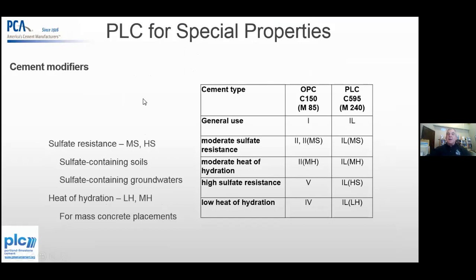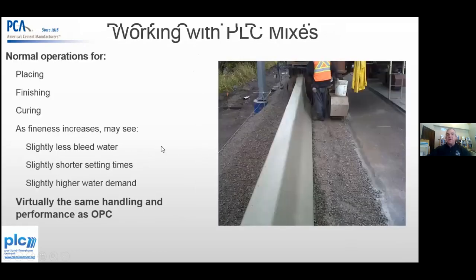Just on its own, the specifications actually allow you to use a IL cement as an MS as well, a moderate sulfate resistance, similarly to a Portland cement, and you can have high sulfate resistance just as you can with an ordinary Portland cement, or you can have a low heat of hydration, IL LH, similar to having a low heat of hydration type 4 cement. Same thing with moderate heat too. So the performance specifications in C150 can be matched with similar performance specifications in C595 or M240 for AASHTO.